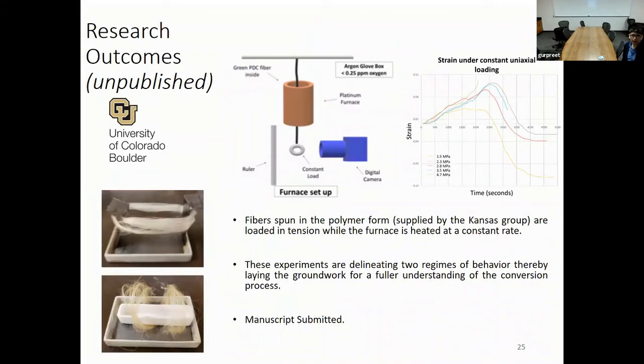And then the second one is the experimental setup that has recently been put up by the graduate students at University of Colorado. This is inside a glove box. What you see in this schematic is a fiber bundle attached at the top, passing through a hot zone, and at the other end of the fiber bundle a constant load is attached. You can observe this through a digital camera, and on the other side there is a ruler. So the idea is that you can basically perform a creep tensile test of pretty much any fiber bundle material.